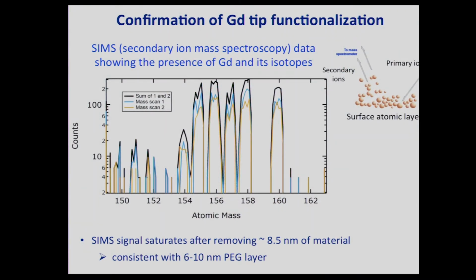And just to confirm that this functionalization worked, we have really nice multi-user facilities at UCSB. We used SIMS, a secondary ion mass spectroscopy measurement, where we took our AFM tip that we think has gadolinium on it, shot ions at it, looked at the emitted ions, did mass spectrometry on those, and confirmed the presence of gadolinium. These are all peaks associated with gadolinium, with the expected gadolinium atomic mass. And we also see that the signal saturates after about 8 nanometers of drilling material away, which is consistent with there being about a 6 to 10 nanometer PEG layer. So those are the next set of experiments that we're going to do.